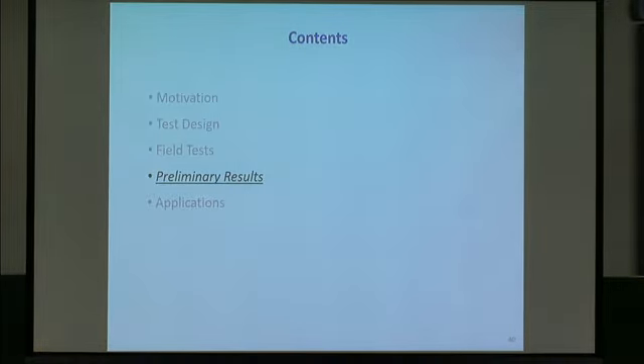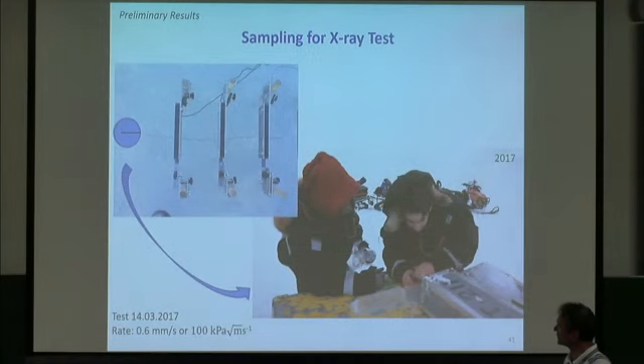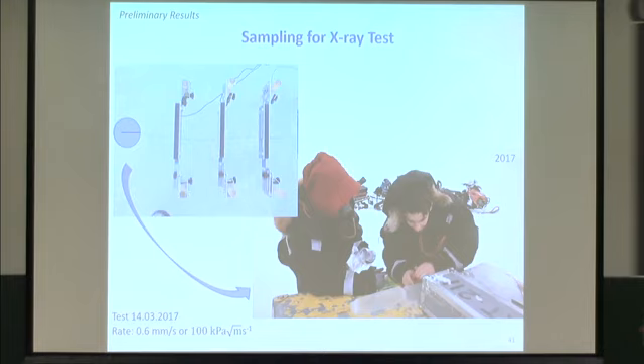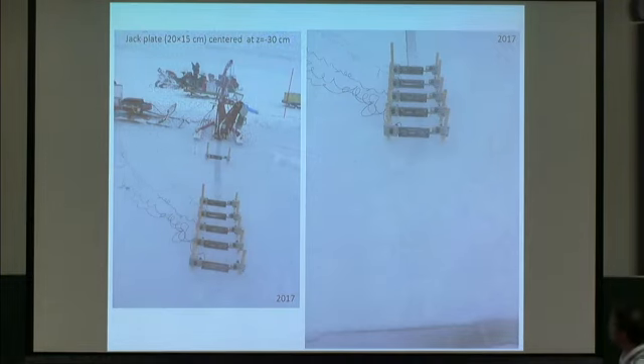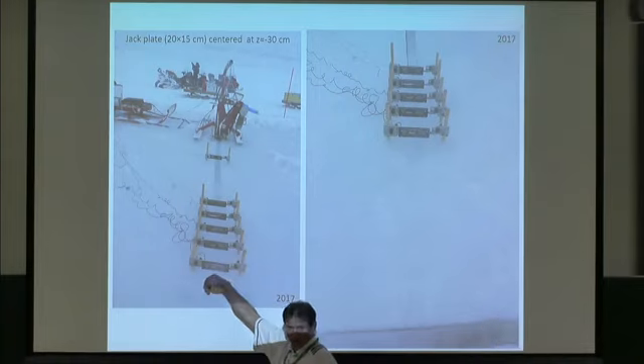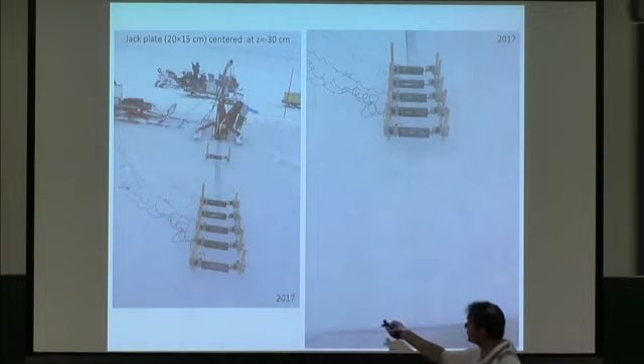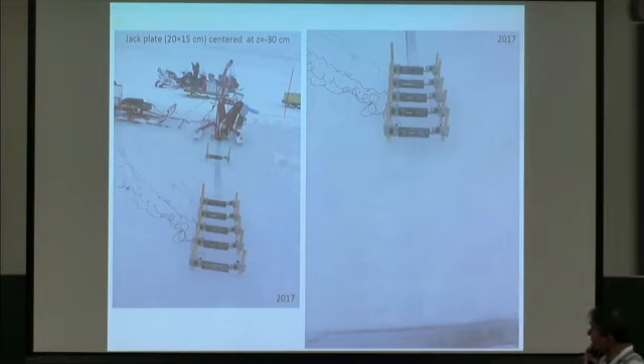So what can we say here about preliminary results? If you now take as an example, okay, I should probably immediately answer your question. What we did here, if you see the jack is here, the distance over here is 5 meters. So we used the ditch witch in to a certain distance. Then we used a chainsaw a little bit further, and then we went over to a handsaw, which was around 1 to 1.2 millimeter wide. And of course, it's very, very important that that is sharp, as we were considering. So there was no way you could run this all the way. So we stopped well before, as we were afraid of interrupting the whole thing.